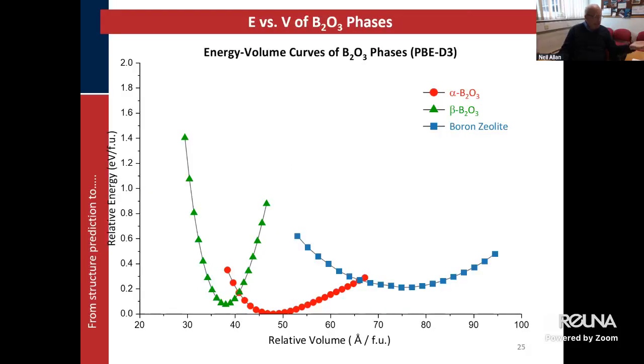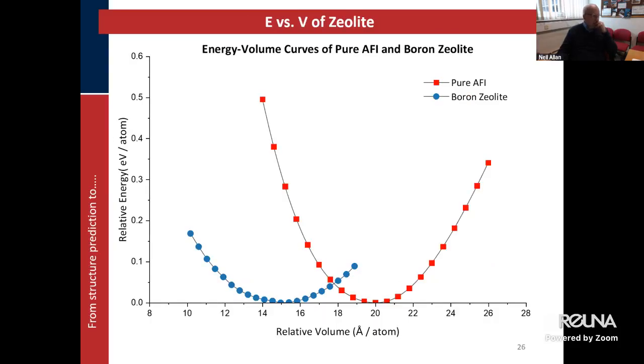And now on this next slide we have the energy volume curves for the alpha form, the beta form, and then our zeolites. Yes, the minimum energy for the boron zeolite is a little bit above that for the alpha and the beta known forms, but not very much so. And here is a comparison of the energy versus volume curves for the boron zeolite relative to the AFI zeolite. Again, we see that the boron structure is a little bit more flexible, with a broader curve than the silicon equivalent.